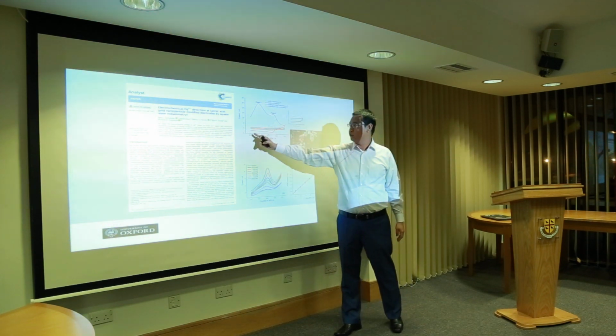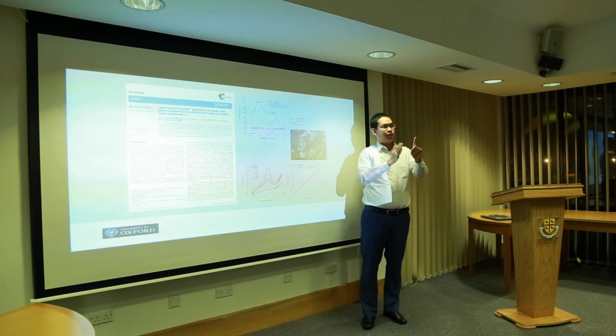You can find the second peak here at about 0.54 that corresponds to the oxidation of the complex. But when you apply a different potential window, from 0.3 to 0.7, you can find the second peak occurs at a different potential. And this is specific only for mercury. So in one system, when you apply different conditions, different starting potential, different accumulation time, also different scan rate, how fast you scan the current, it will lead to a different position for specific metals. So you can detect in both ways.